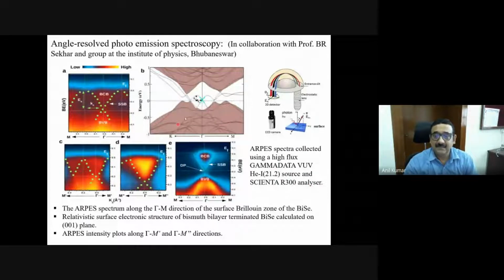And my collaborator, Professor Umesh Waghmare from JNCASR, did the density functional theory calculations, and this was predicted to be a weak topological insulator. We did the angle-resolved photoemission spectroscopy study, and that matches with our theoretical data, and then we established that this is a weak topological insulator.